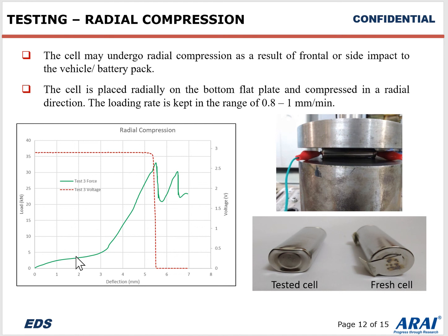In the first stage, the load increases linearly to eliminate the possible gaps within the cell, and in the second stage, the pores in the active material start filling. So this is the second step, from 2 to 4, where the pores get filled and thus show a curve pattern like metal foams.